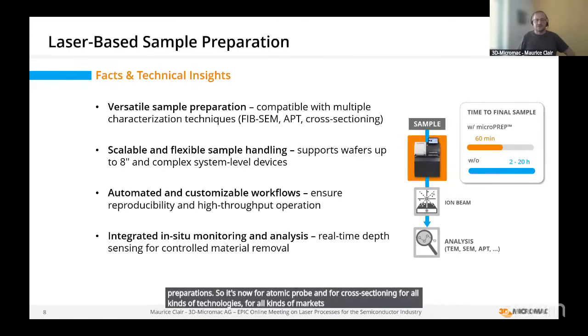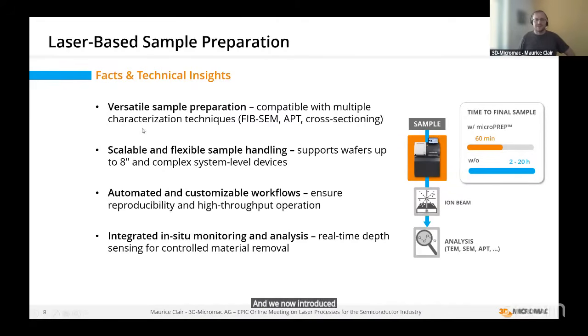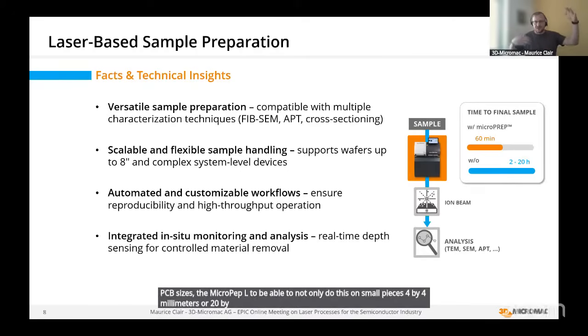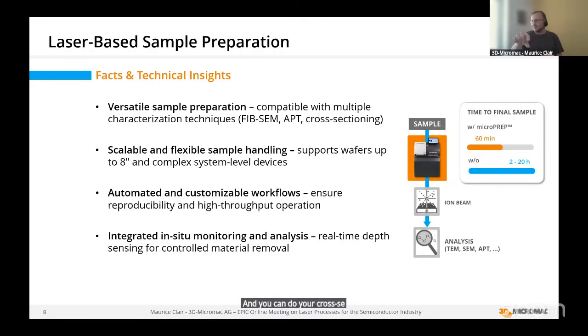And we have now introduced a new product which supports larger wafers and PCB sizes, the Microprep L, to be able to not only do this on small pieces, 4 by 4 millimeters or 20 by 20, but also on large PCBs, 200 by 200 millimeters, for example, which can be put into the machine, and then you can select which area you want to analyze, and do your cross-section or your sample preparation directly from that.